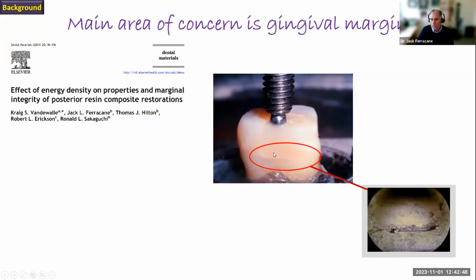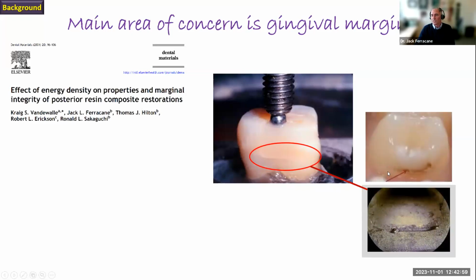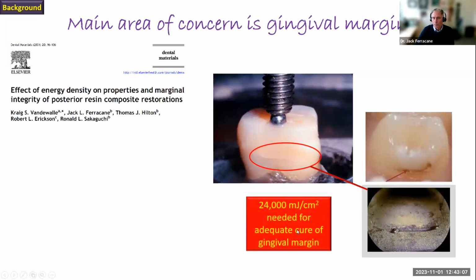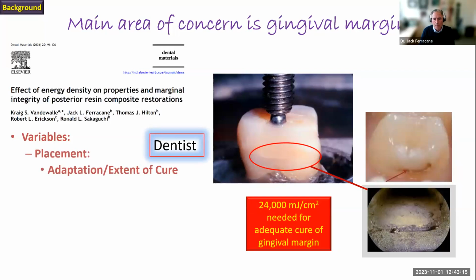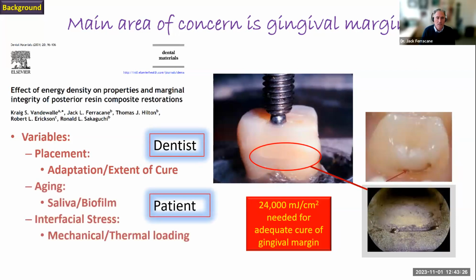And we took impressions and made replicas for electron microscopy before and after. And you see this type of washout of the composite here at the gingival margin, which is very reminiscent of what is often seen clinically, where we see decay forming in this same area. And the study showed he needed about 24 joules per centimeter squared for adequate curing of the gingival margin, so this wouldn't happen. So there's several variables: the placement of the restoration, so how well this material is adapted to that margin, and then extremely critical is how well cured it is. And these are in the hands of the practitioner, the dentist.